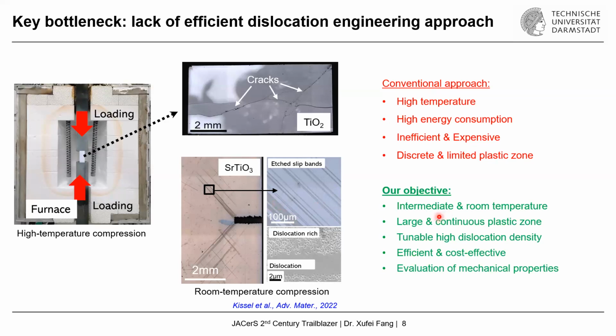So in our group, we have been trying to achieve the following objectives. Instead of doing high temperature deformation, we're thinking whether we can achieve intermediate temperature or even room temperature deformation to accelerate this whole process. And also, compared to the discrete and rather limited plastic zone, can we achieve a large and continuous plastic zone for easy handling of the samples? It has also been shown in literature that the higher the dislocation density, the more beneficial for both the mechanical and functional properties. So in general, we would like to make the efforts much more efficient and cost effective.